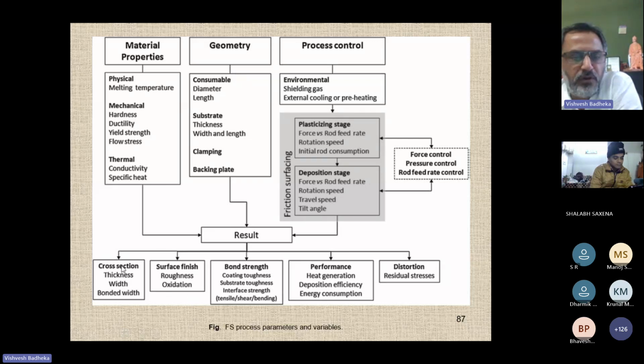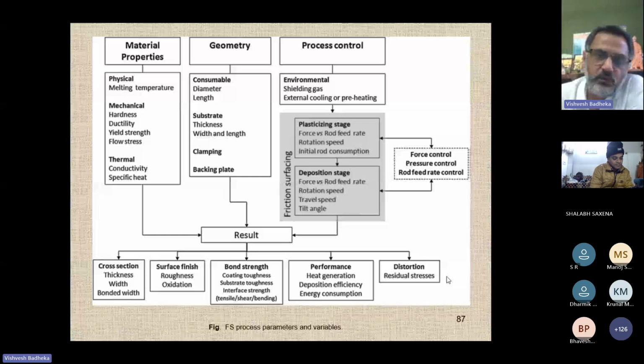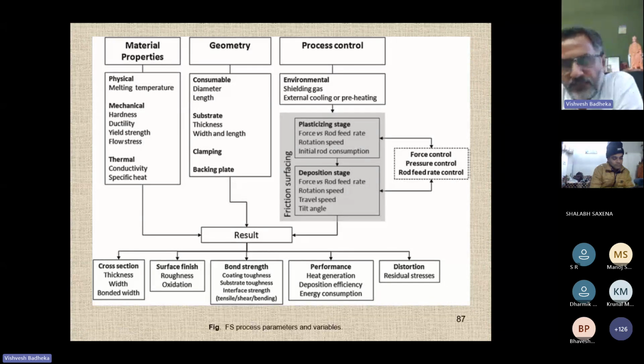All together, the geometry, material property and process control will affect what? The cross section, the thickness and width of the bead, bonded width, surface finish, roughness, oxidation, and the bond strength: tensile, shear, bending, and the performance in terms of heat generation, deposition efficiency, residual stresses. All those things are important in friction surfacing.